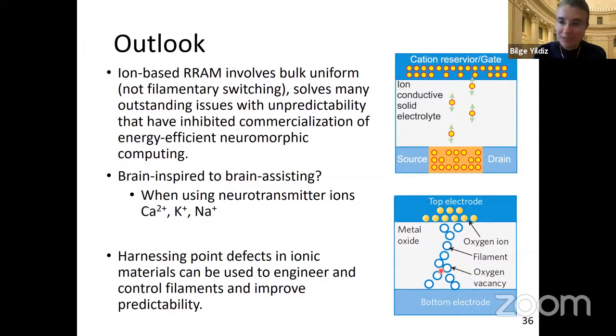And on top of this, if you add dopant engineering, that is what I've shown in the last slides, where we are inserting dopants that, regardless of the microstructure, are chemically so distinct that they can strongly localize the formation of the vacancy. So gold being in aluminum makes such a big difference in the ability to pick up the electron of an oxygen after you remove the oxygen, that reduces the vacancy formation energy, or makes it much easier to form the vacancy, and becomes a pinning site. So that's what we call dopant engineering, that we are inserting these additional elements that are chemically very distinct from the host and can really pin the formation of these vacancy conducting paths. I hope that helps to clarify.